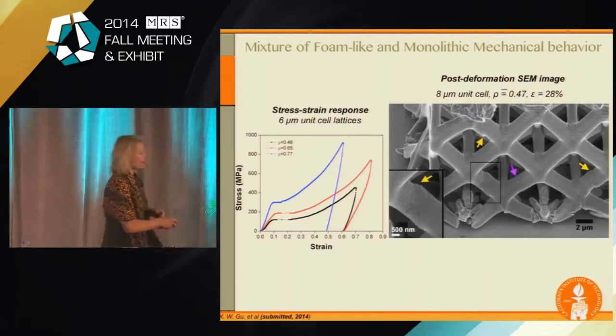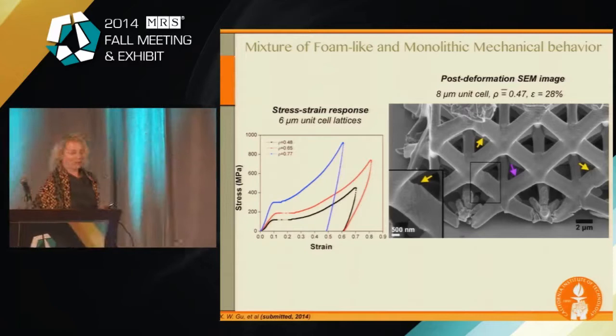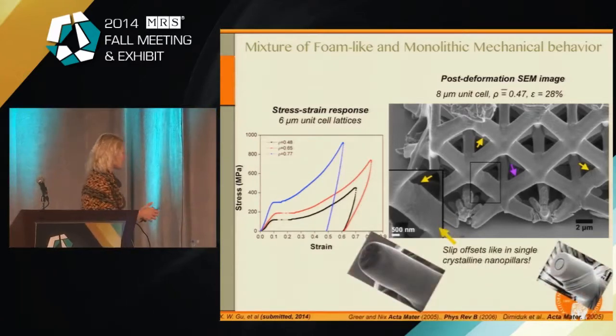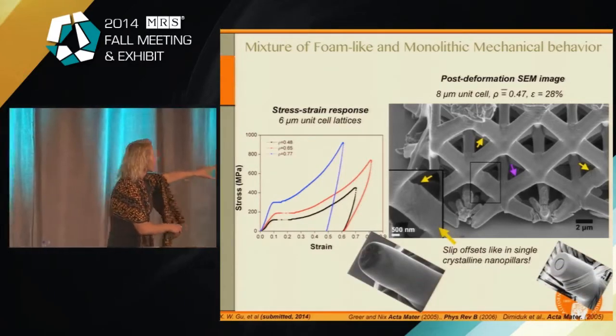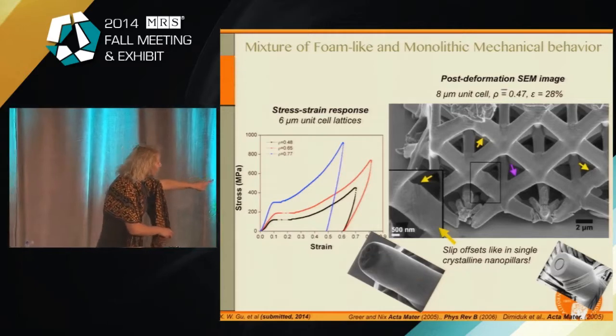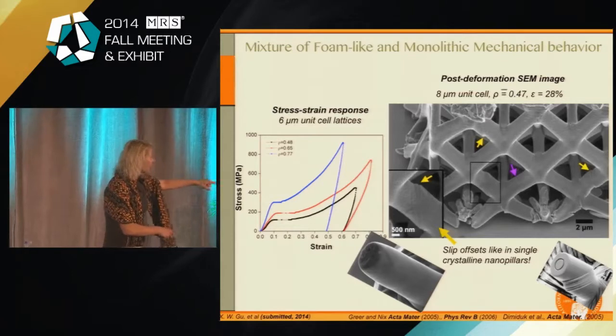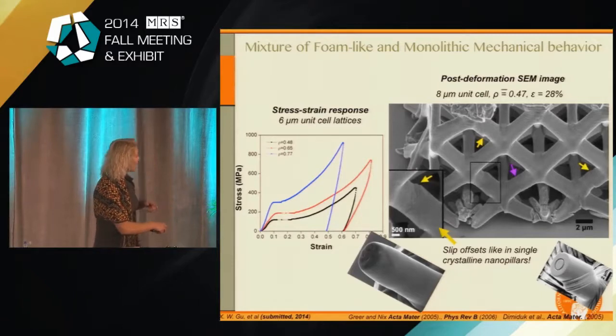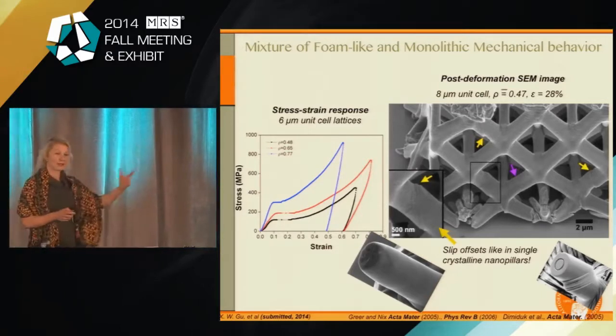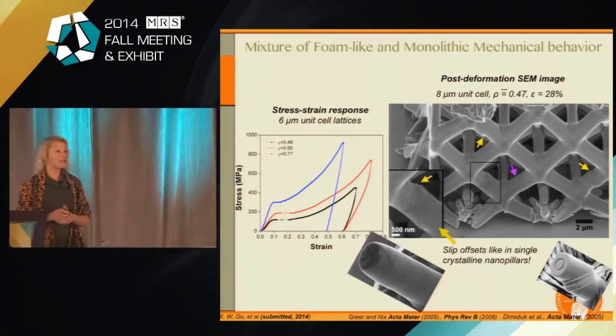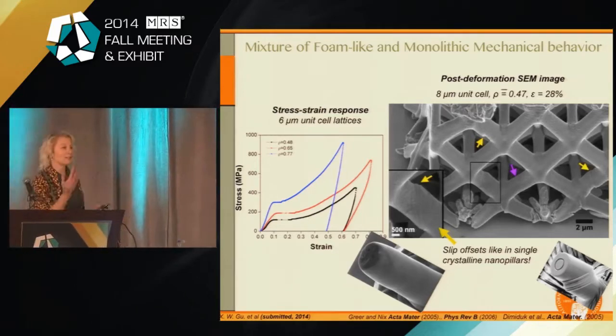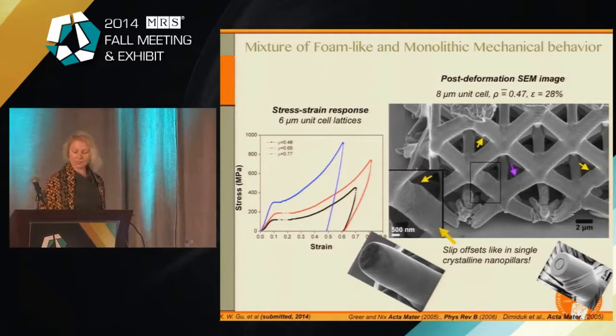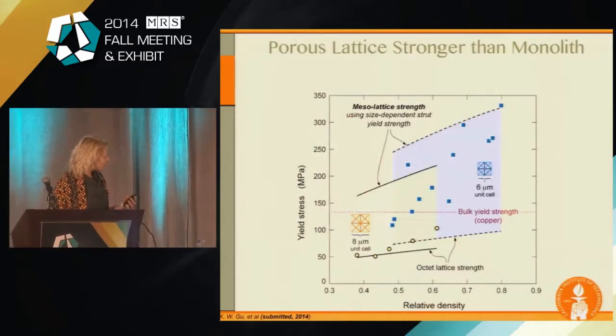I'm showing you these crystallographic slip lines. The reason I brought up the nanopillars is because this pattern looks very much like the very first gold nanopillar that I made when I was a little grad student. And this is the very first micropillar that was made out of nickel earlier, by Mike Uchic. You can see that these are very similar crystallographic slip lines that occur in a mesolattice as in the individual structure. So even under complex stress states, under complex loading conditions, you already see this behavior. So now let's see what this means.